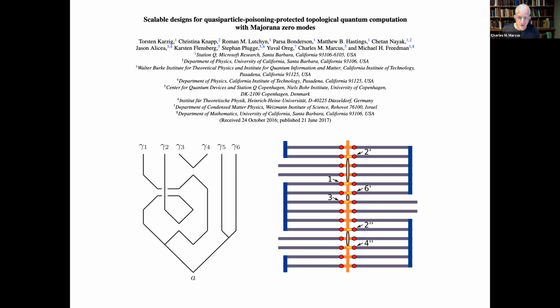That said, a lot of the theoretical work that's happened in the last few years has acknowledged that when we make these wires, we have to apply a large magnetic field along the axis of the wire for 2 reasons. One reason is that when it's along the axis of the wire, that puts the magnetic field in the correct direction perpendicular to the spin orbit field, which opens up the gap and creates the topological state. That's one good reason to put the magnetic field along the axis of the wire. But the second good reason is because that's a direction in which the superconductor is very thin. And in that direction, the magnetic field does not drive the superconductor normal.